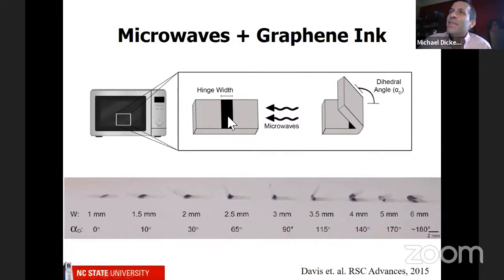But in the end, we found that graphene is a really good absorber of microwaves, like really good. And if you put these graphene inks on these materials and you expose them to microwaves, they will get hot and fold. Depending on the width of this region, which is labeled W here, you can go from 0 folding all the way up to almost 180 degrees of folding. This was kind of neat, and this happens really, really fast.